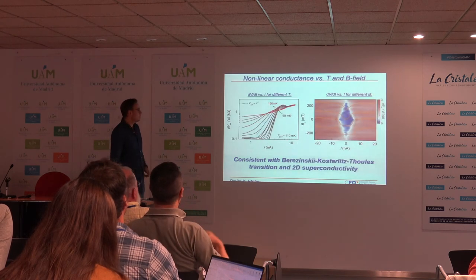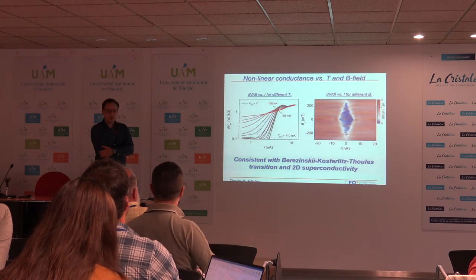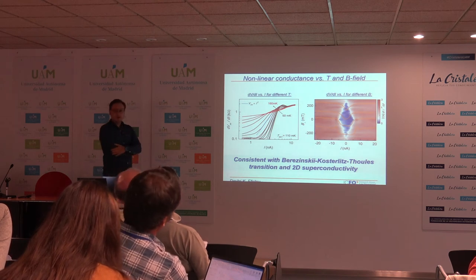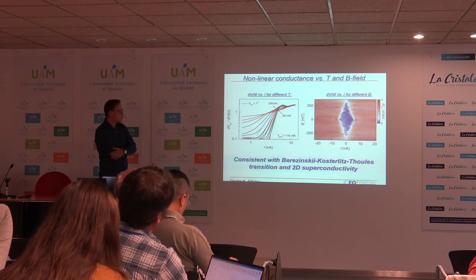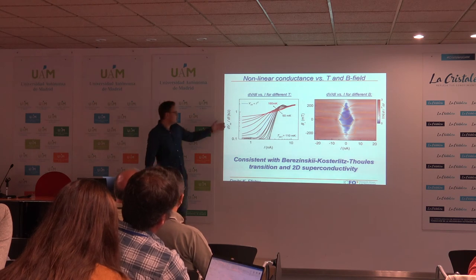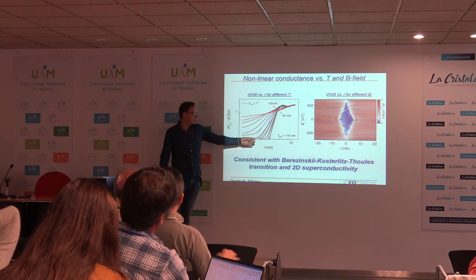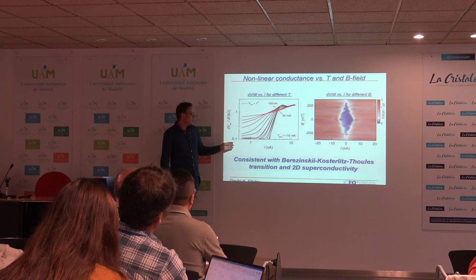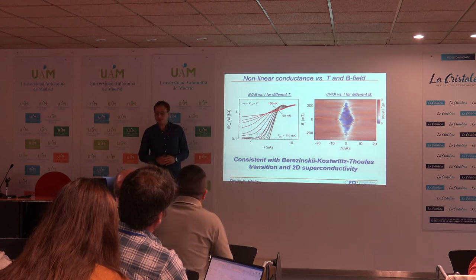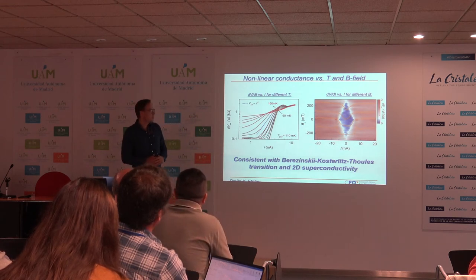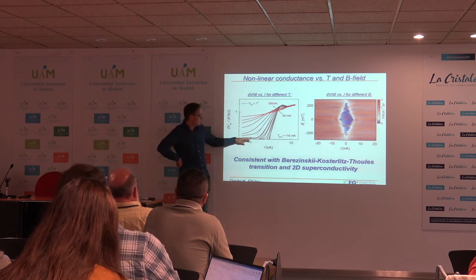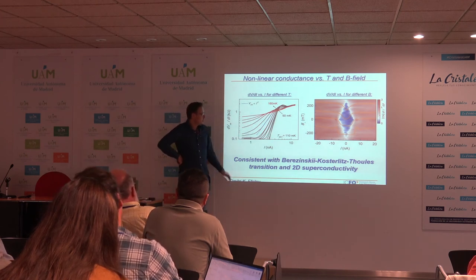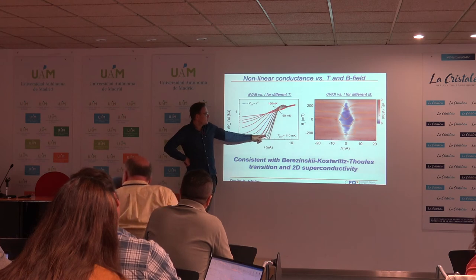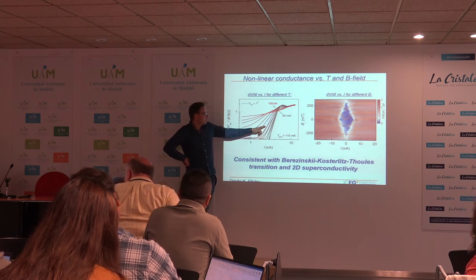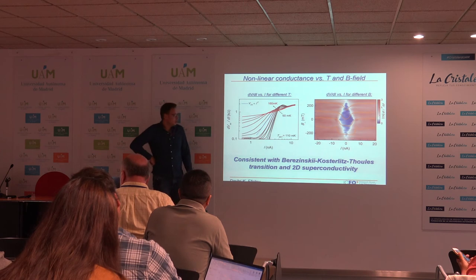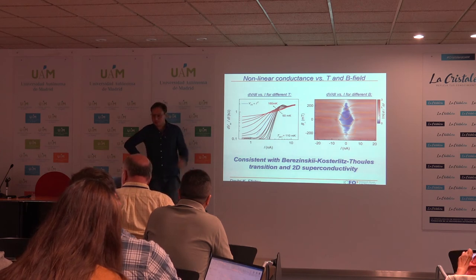Okay, and last but not least, we also like to measure nonlinear conductance in the device, so this is dV/dI as a function of current. And as you can see, there is a really, really sharp transition when we reach the critical current of the system. So the transition is much sharper than expected for a 3D superconductor. So the transition really is consistent with the BKT transition for 2D superconductivity.